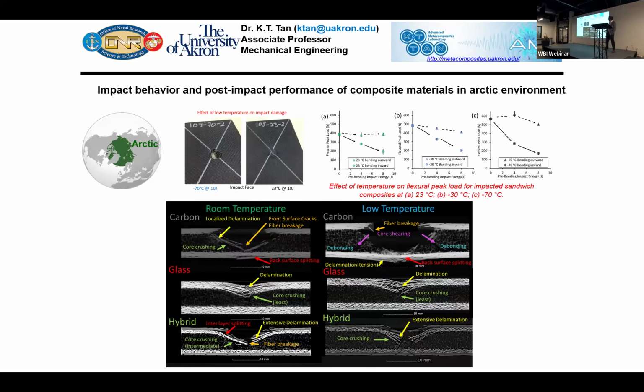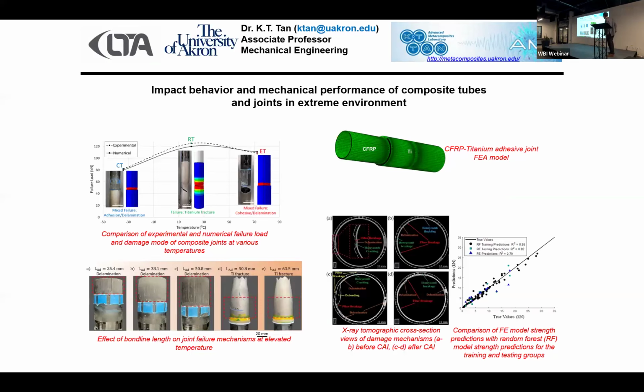And on the next slide is another project from their lab where you're looking at the interface of a composite and a metal. So wherever you have a joint between a titanium and a carbon fiber composite, how does that joint fail? They've developed a lot of finite element analysis for these complex failure mechanisms. They do XRT to characterize those materials, and they've also developed predictive models for these systems, combined with their own results, their computational data, and results that are out in the literature, in order to develop advanced analytical prediction for these metal composite joint failures.